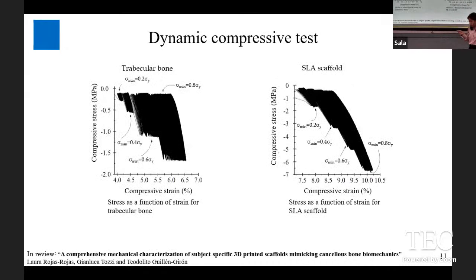Now we also calculated the hysteresis curve for the samples, and in the hysteresis curve you can see if there was deformation accumulation on the sample, if there is, let's say, a gap over here on the compressive strain, but this didn't happen for our SLA scaffold, so it also endured these types of loading. And you can see here the one that we got for bone. Again, there is an increase in the stress, and that's because we also attributed that to the trabecular thickness that was found during fabrication.